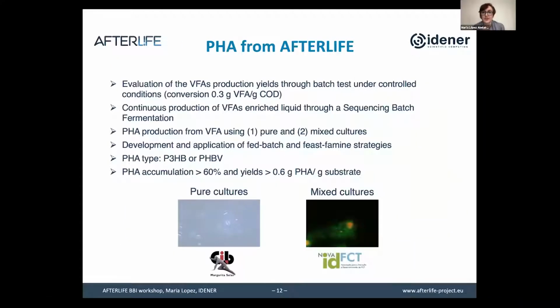So how do we produce PHA in AFTERLIFE? The first step, if you remember, was the production of the volatile fatty acids. Here we achieve good results in the conversion of the suspended solids separated from the wastewater into volatile fatty acids. Now we have these volatile fatty acids, and we use them for the production of PHA. We use two alternative bacterial processes. The first one is the use of pure cultures, that is single strains able to accumulate the polymer, or the use of bacterial consortium for the production of the PHA.